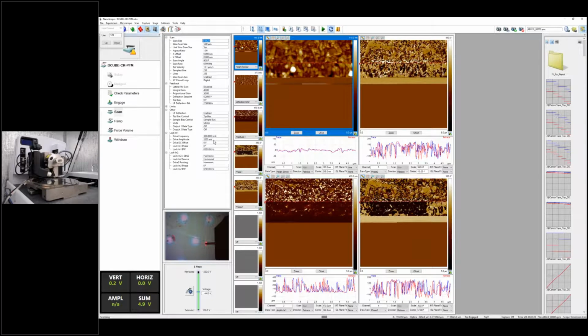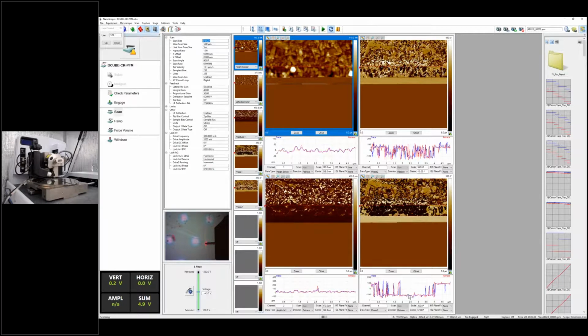So now we didn't apply any DC voltage, but just use AC voltage to scan, which in PFM is quite often called reading. So we are trying to read this piezo response from these different areas. You can see once you get into this area, the phase is dominantly minus 90 degrees, while in the neighboring area, which we didn't write, it's basically random. You have plus and minus 90 degrees phase distributions.